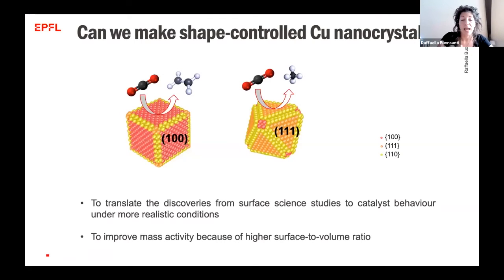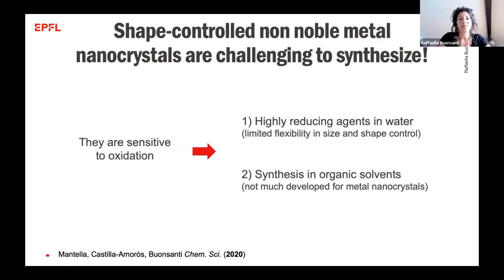So what we thought was, okay, why don't we make copper nanocrystals as cubes and as octahedra in order to learn if we can translate these discoveries from single crystal studies into more realistic conditions, and see also if we can learn something more about the size dependence of this reaction. Now, it turns out that while we have a huge library of noble metal nanoparticles, things start to be a bit more complicated and limited in terms of shape control for non-noble metal nanoparticles. The problem is that most of the chemistry for metal nanoparticles has been developed in water, and non-noble metal nanoparticles will oxidize in water.